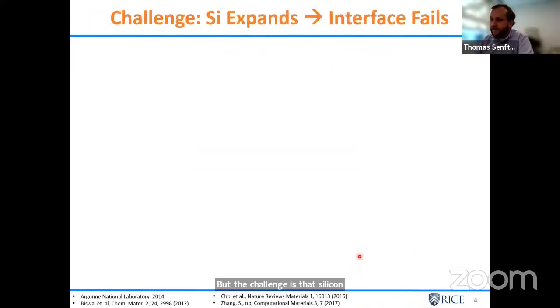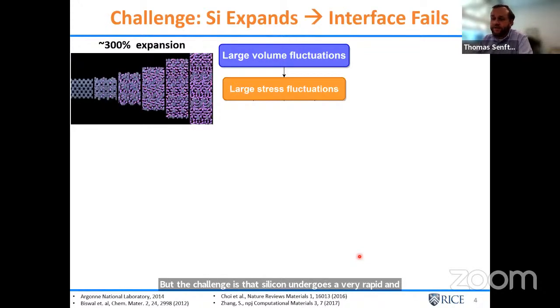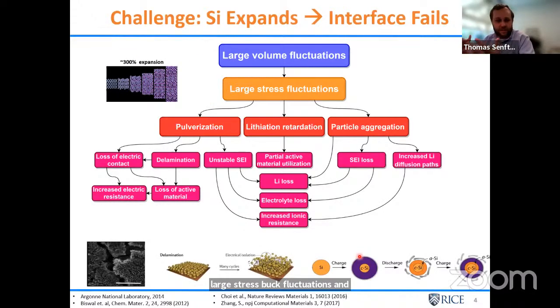So we're interested in applying simulation to design better anode materials in batteries. And here I've just highlighted a couple of the common anode and cathode materials. And I want to point out, we're very interested in silicon because it has a theoretical capacity that's almost 10 times that of the current state of the art, which is the graphite materials. But the challenge is that silicon undergoes a very rapid and large volume expansion upon lithiation. So you can get a lot of lithium into the silicon, but then the silicon expands, and that causes quite a lot of problems. You have large volume fluctuations, large stress fluctuations, and ultimately that destroys a lot of the interfaces in your electrode material. And it leads to a host of problems that really cause the electrode to fail very quickly.